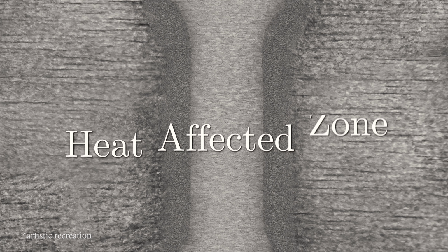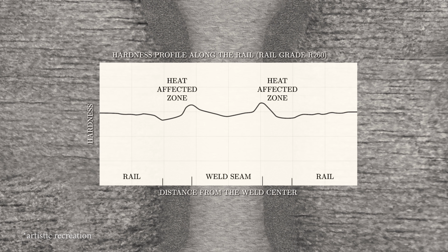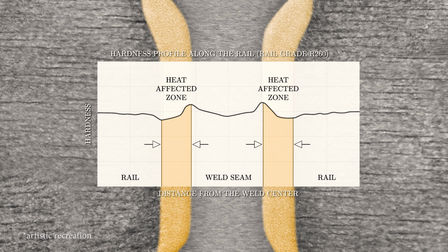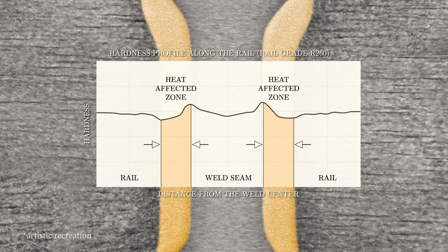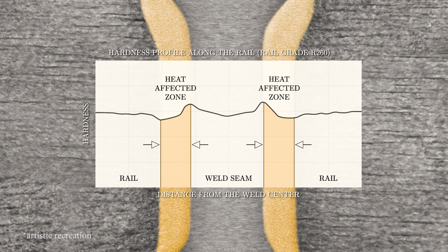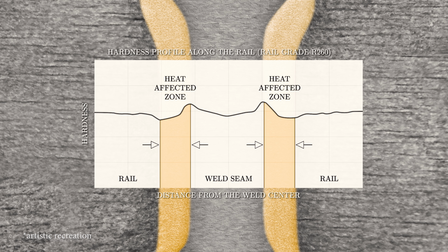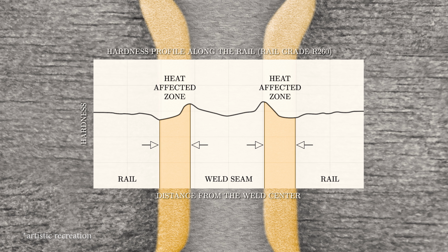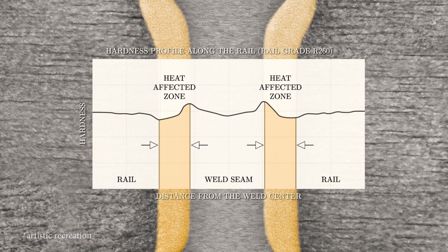The final zone is in between the normal rail and the thermite steel. This steel didn't melt, but it received enough heat that the crystal structure changed, resulting in a smaller grain structure. This is known as the heat-affected zone. If you measure the hardness across the weld, this zone is actually the weakest, both in terms of hardness and yield, the amount of force it takes to permanently deform the steel. So if a weld breaks, it's almost always here.